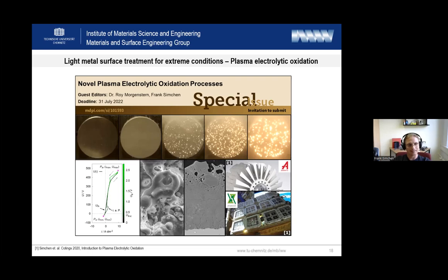Gas permeation. It's possible that the gas comes through the coating to the substrate because it's a little bit like a thermal spray coating. You still have your crack network. That's why you're using a sealing step. Such a sealing step was also used in producing this turbomolecular pump.